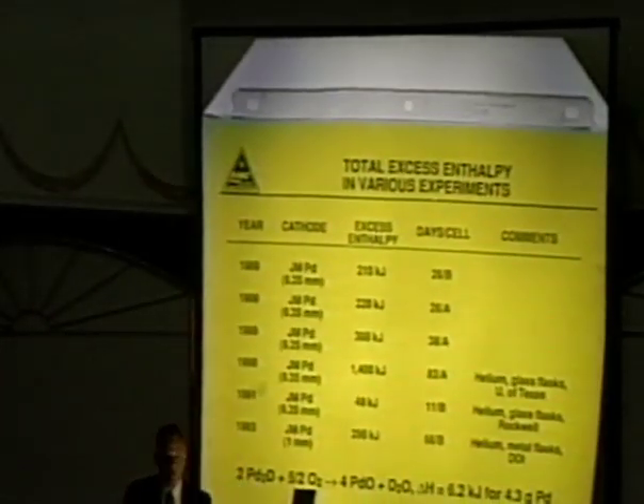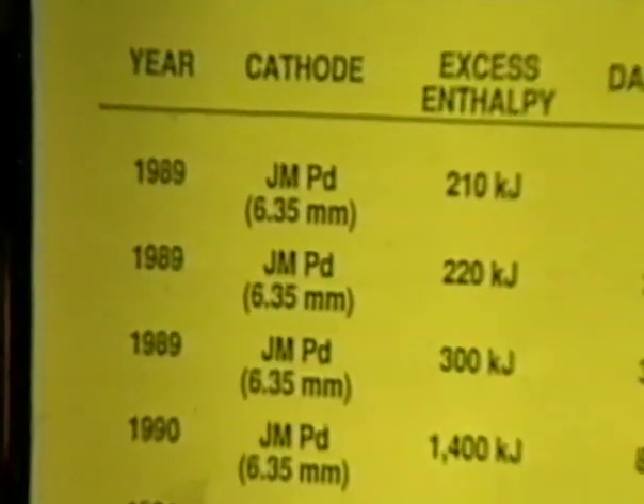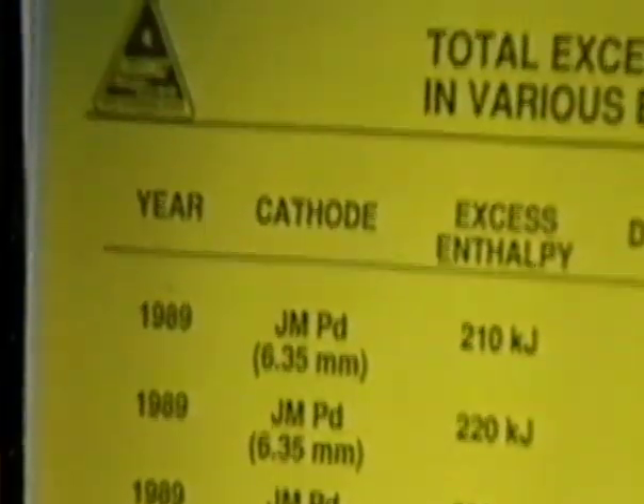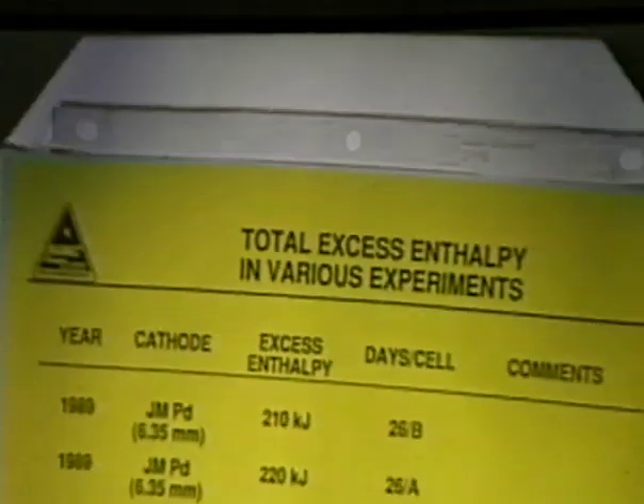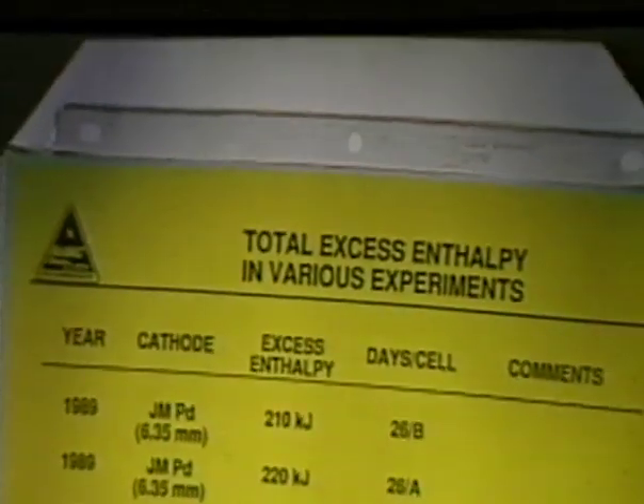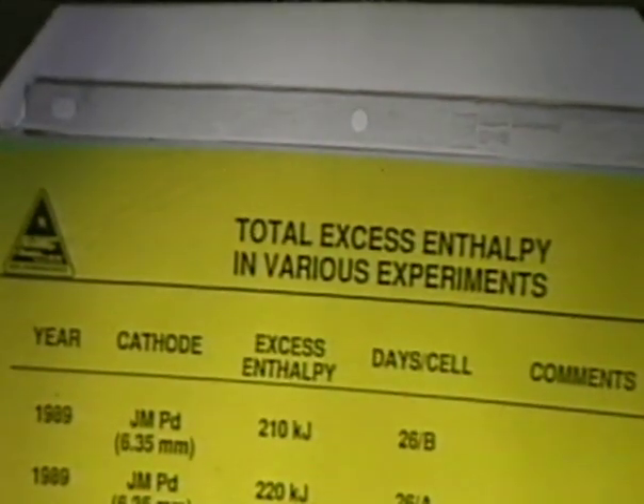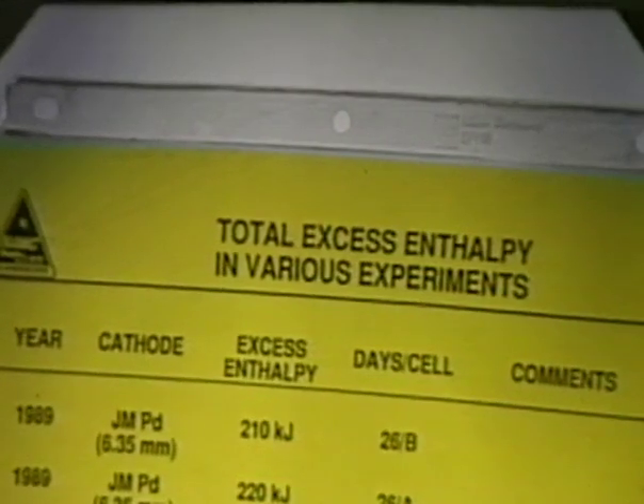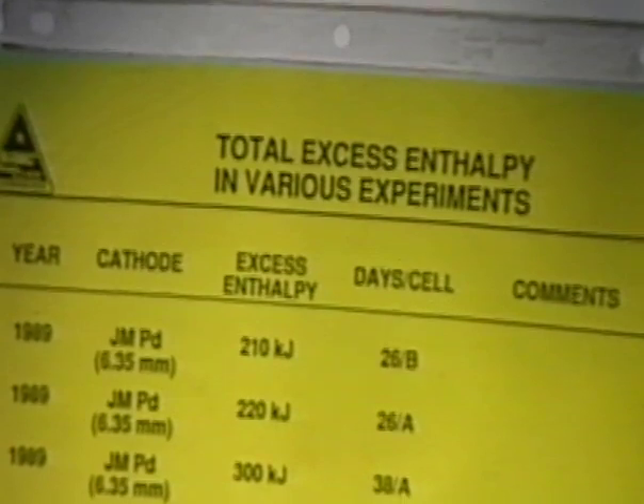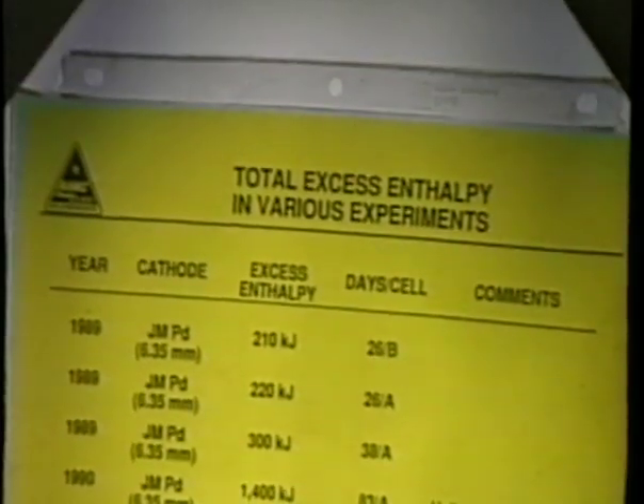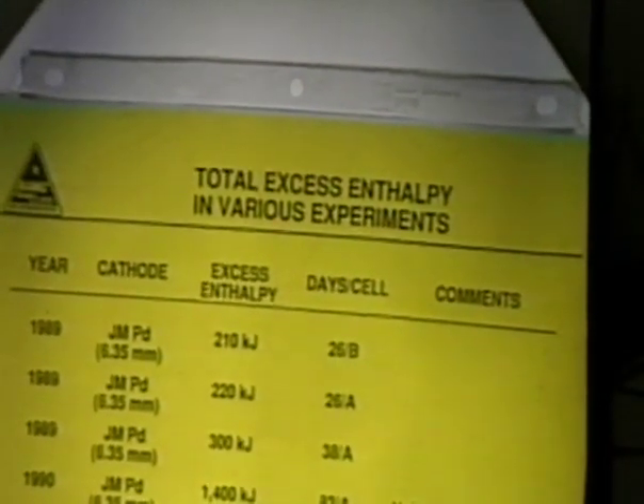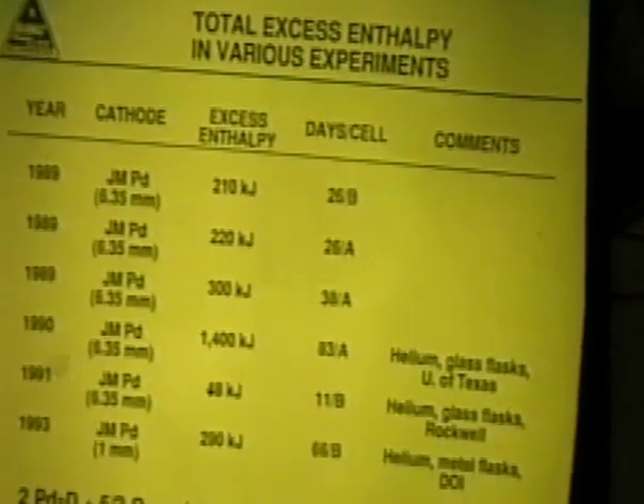If you integrate the power that we measured over the time, you can get the integrated energy. Our first experiment was 210 kilojoules, and the others were a little bit higher. Where we measured helium for the first time, we ran that for several months, and that integrates to 1,400 kilojoules, or 1.4 megajoules of total energy. And that's when we did the first helium study.